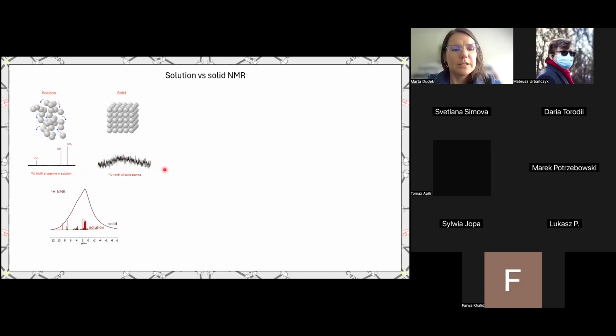So this is not something that we want. And the line widths in solids are very wide. So the spectra are not at all resolved, one may say. And this is all because of the two main culprits, dipolar couplings, interactions, and chemical shift anisotropy. So both of those phenomena are not averaged out as they are in solution, and we have to do something with them.